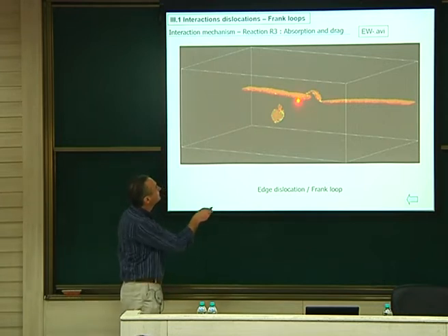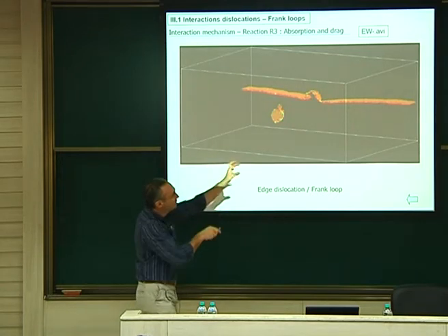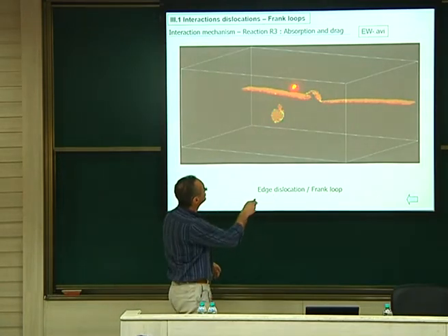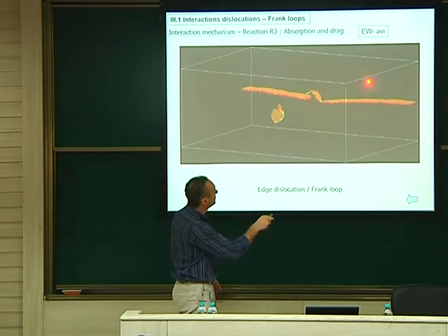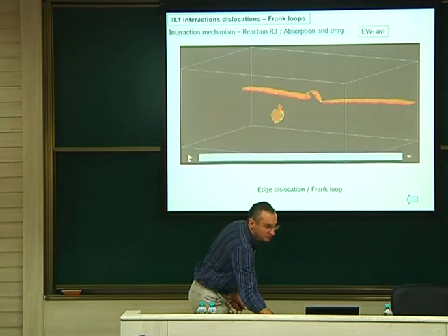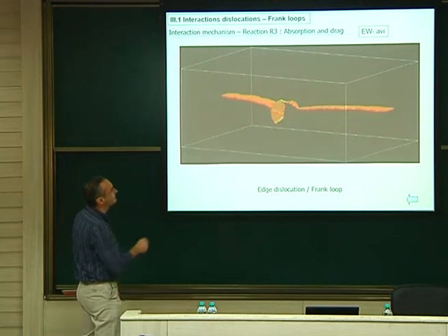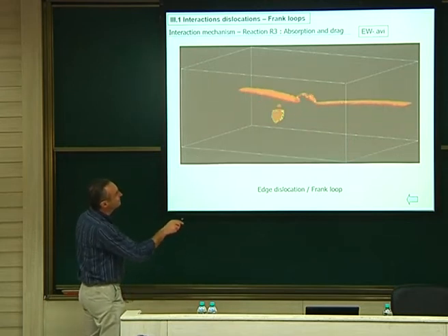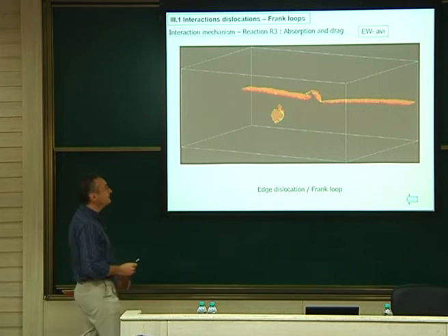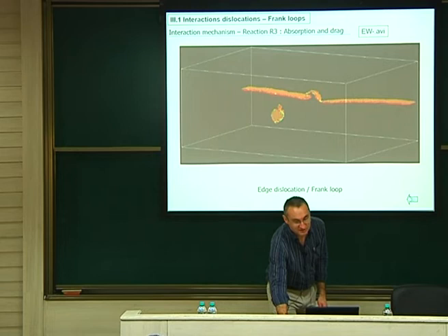And the dislocation is now no more planar, but it can glide. So it means that here somewhere, this point corresponds to that point. This point corresponds to that point. Here, I think this jog will move along the Burgers vector corresponding to the reaction between the two. So it is pinned in a line. This can only glide in a line. You can see the movie again. But it's not very much hardening. The hardening is very weak again. You can see that the dislocation is not much bent. And it can pass through quite easily, like that, and move away. Okay? That's a small mechanism, let's say, to remove the density of loops.